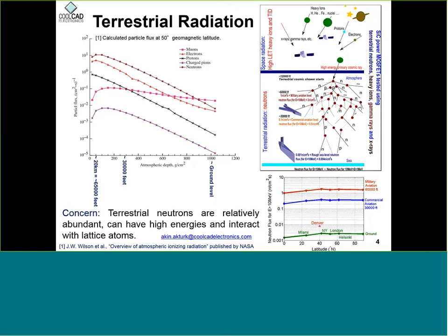On the left, you can see what's in the natural background radiation. The x-axis is atmospheric depth, which is correlated to the altitude. And on the y-axis, you can see the flux per centimeter square per second. And as you can see, there are lots of neutrons at high altitudes. And at the ground level, actually, you have more muons, but they cause a minimal amount of failures in power devices. They can also cause failure, but since they are much lighter and they do not interact much, their failure rates are lower. And in silicon devices, they are more associated with causing failures at low biases. And for mid to high range biases, neutrons cause the failures in silicon.